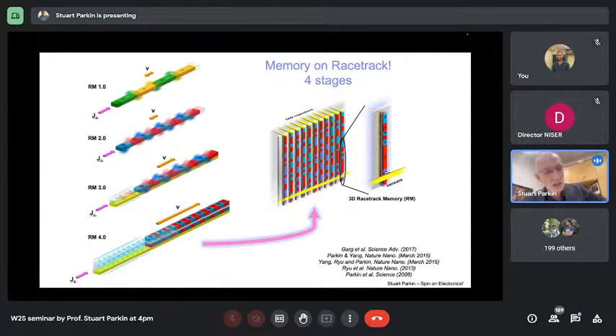Now, what was a very interesting discovery a few years ago was that if you now create a structure, the same cobalt-nickel multilayered structure, and place that multilayer on this yellow layer, which is a layer of platinum, then when you pass current through this system, the current moves in the opposite direction and moves much faster. And the mechanism for moving these domain walls is something that we unraveled together with some other groups around about the same time.